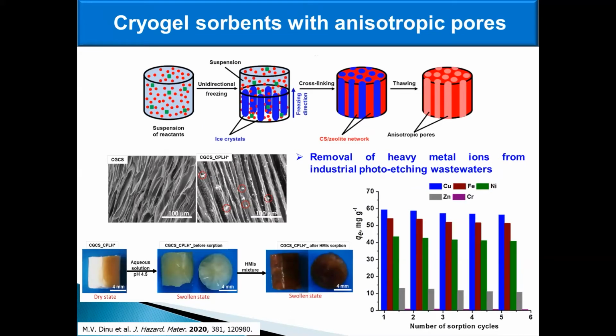The chitosan-based composite cryogels exhibit also great potential in treating real wastewaters resulting from photoetching processes in which copper, zinc, nickel, iron, and chromium ions are the prevalent ions. The effect of several parameters such as sorbent dose, contact time, pH, initial metal ion concentration, temperature, and desorption properties have been clearly established. And it was shown that the ion-imprinted sorbent exhibits a remarkable chemical stability during the loading and eluting stages of heavy metal ions, the absorption capacity remaining almost constant even after the fifth cycle of absorption.